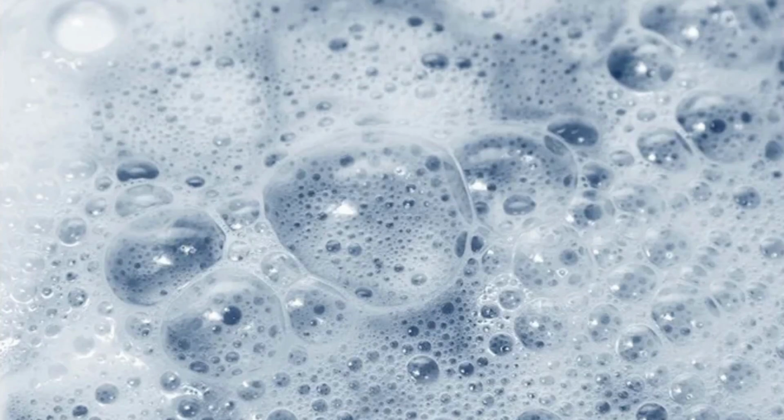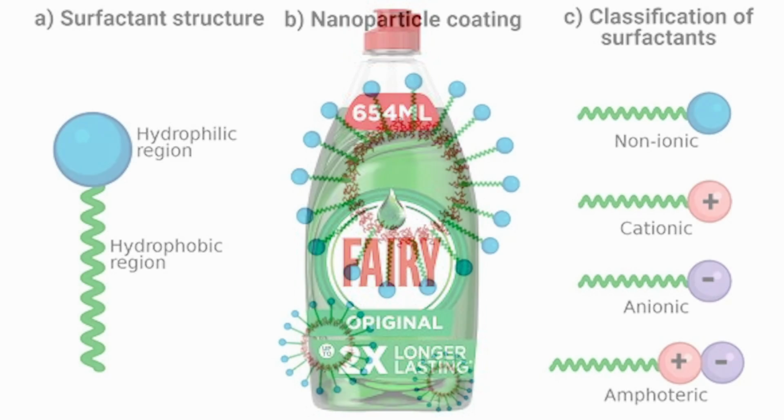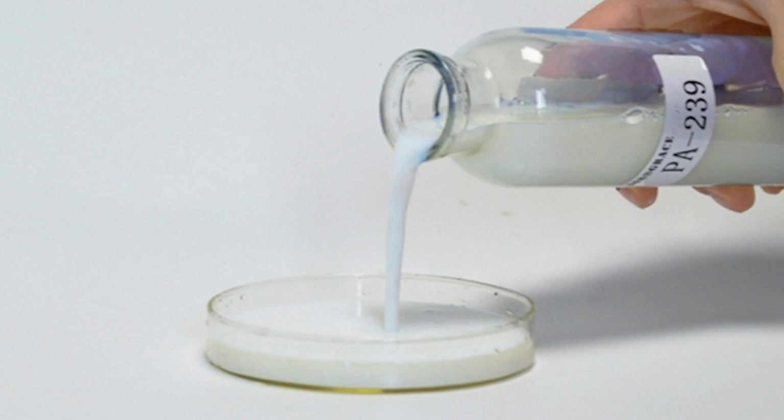What we do to make acrylics water soluble is to introduce a surfactant. Think Fairy dish soap and you won't be far off. Surfactants like this work by having a hydrophilic, water-loving or water-soluble section or head, and a long hydrophobic, that's fat-loving or organic solvent-soluble tail. This is how detergents clean things, by making fats or other water-insoluble dirt able to be washed away with water. They form a bridge between the two immiscible components. Our surfactant can thus surround our submicron-sized acrylic spheres and create a mixture known as an acrylic emulsion that is the base for our water-soluble paint.